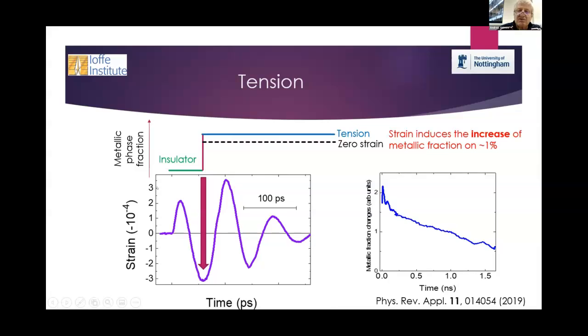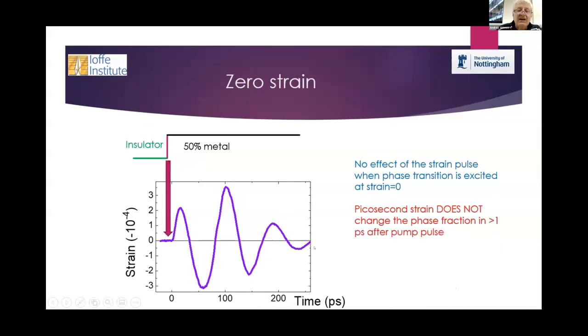It's interesting that if we excite it here, before the strain pulse, the system goes to some metastable state very quickly, in much less than 1 picosecond. So we excite here, and then in less than 1 picosecond we measure what is happening, and actually we see that nothing happens.